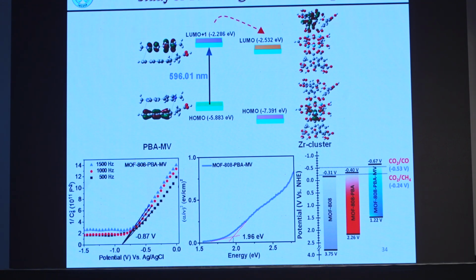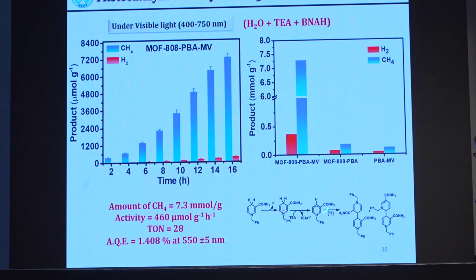So I have done the Mott-Schottky analysis to understand how it is happening and the band structure. I'm not going to spend much time, my time is limited. So I have used this kind of sacrificial agent, which is very, very important. This is 1-benzyl-1,4-dihydronicotinamide. The oxidation potential is only 0.29 volt, so it can quench the hole efficiently. And now, instead of CO, we are getting 8 electron, 8 proton reduction to get methane. Okay? We are getting methane now. So 7.3 millimole per gram, turnover number is 28, and the activity is also quite high.